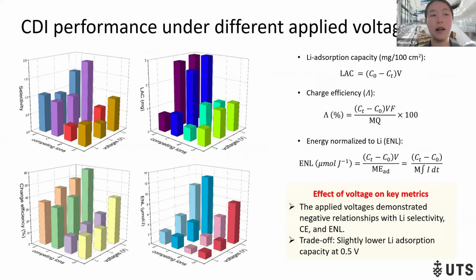Then I also did a CDI test using the AC-ZIF8-polydopamine electrode under different applied voltages, and I compared the energy input. I tested the lithium adsorption capacity, charge efficiency, and energy normalized to lithium as metrics to evaluate the performance of CDI. I found that the applied voltage demonstrates negative relations with lithium selectivity, charge efficiency, and energy normalized to lithium. And the trade-off is the slightly lower lithium adsorption capacity under the lower applied voltage.